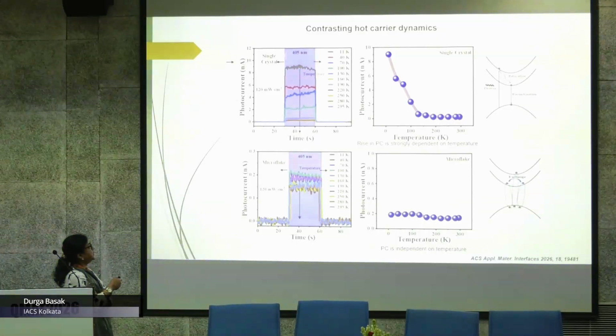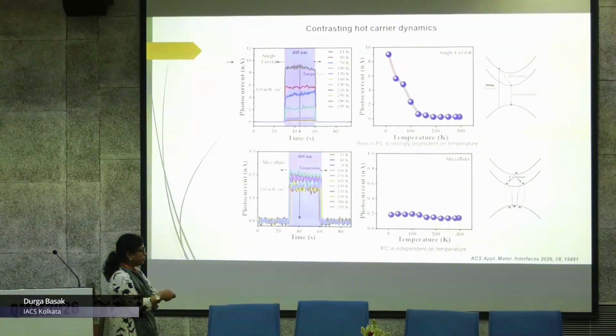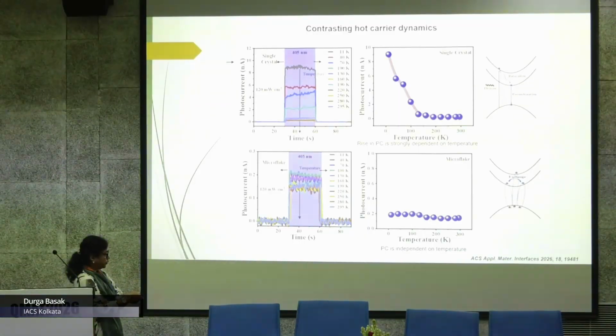So we have done photocurrent transient experiments where we have illuminated the samples with light of 405 nanometer with power 120 milliwatt per centimeter square, and we did this experiment at different temperatures. We found the maximum photocurrent and plotted it as a function of temperature, and this gives a very interesting plot. When we cool the sample up to a certain temperature, photocurrent remains the same, but below that photocurrent sharply increases. So it means that below a certain temperature the interaction is less, so it gives rise to high photocurrent. But in case of microflake, the photocurrent remains almost temperature invariant in the temperature range we studied.